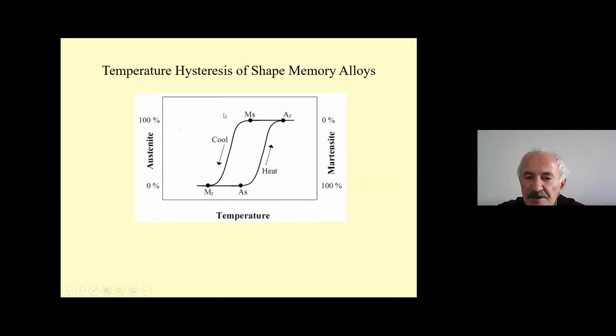As I mentioned, on cooling, thermal-induced Martensitic transformation occurs, and the transformation starts at the MS temperature and is completed at the MF temperature. MS is the Martensitic start and MF is the Martensitic finish temperature, and below the MF temperature, the material is in the complete product Martensitic phase. On heating, reverse austenitic transformation occurs, starting at the AS temperature and completed at the AF temperature. Over the AF temperature, the material is in the parent phase region completely. As you can see, the MS and AS temperatures, the Martensitic start and austenite start temperatures, are not the same in Martensitic transformations.